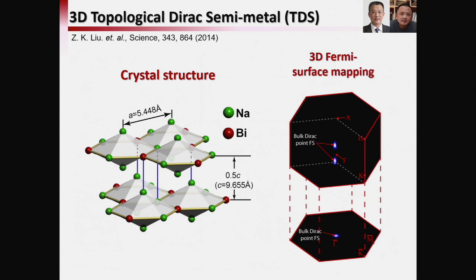The first one is on sodium bismuth, in collaboration with Xi Dai and Zhong Fang from IOP, Chinese Academy of Sciences. And we mapped out a three-dimensional Fermi surface. Typically, in ARPES you see, we only show the two-dimensional Fermi surface map. A three-dimensional Fermi surface map is much more time-consuming and harder to do. But in this case, we have to do it because the two Dirac points are actually separate in the z direction. If you project it into the two-dimensional Fermi surface, you only see one. Then you miss the information.